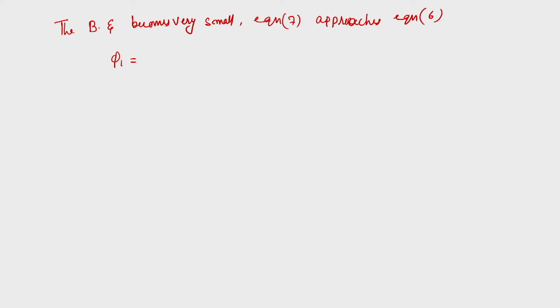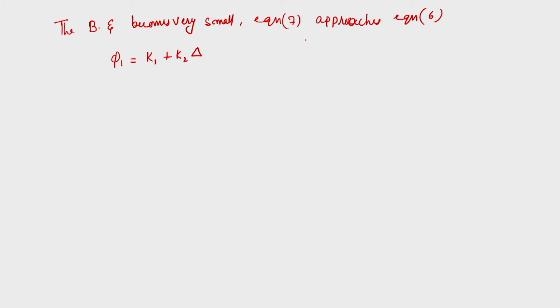So, that is a linear function of the parameter delta, that means phi 1 is equal to k 1 plus k 2 into delta, where this parameter delta which we have discussed, I think it is lecture 3, the deformation zone parameter. So, for your wire drawing operation it can be related as d naught plus df, the final diameter, by d naught minus final diameter into sin alpha, which you can say is almost equivalent to 4 alpha by epsilon w.